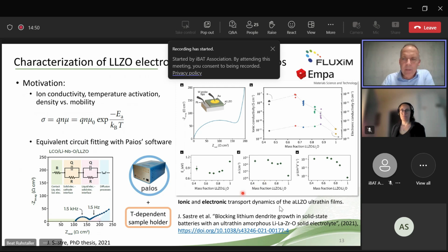And I would like to mention that already a few years back, we had a customer, or let's say a research partner at EMPA Dübendorf, which already purchased our measurement instrument and applied it to novel electrolytes for solid-state batteries. What the colleagues there, with Giorgio Di Sastre, a PhD student, did with the instrument was typically combine it with a temperature-dependent sample holder to measure the conductivity of the ions in these electrolytes over a broad range of temperatures, because it's interesting to understand also the behavior at very high temperature, and then the conductivity usually is much reduced as you go back to room temperature.